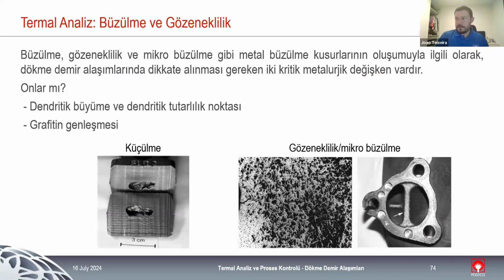And this is just to illustrate normally the big problems that we have during cast iron production, the shrinkage problems. Shrinkage is basically a small area of the cast part that we are producing that at some point during solidification was isolated. And it was isolated because of dendritic growth, and we saw that every alloy grows as a dendritic structure. The branches close early on during solidification, and they isolate a small area of the cast. And we have a shrinkage problem later on because we don't have any liquid metal to expand and to counteract the contraction of the